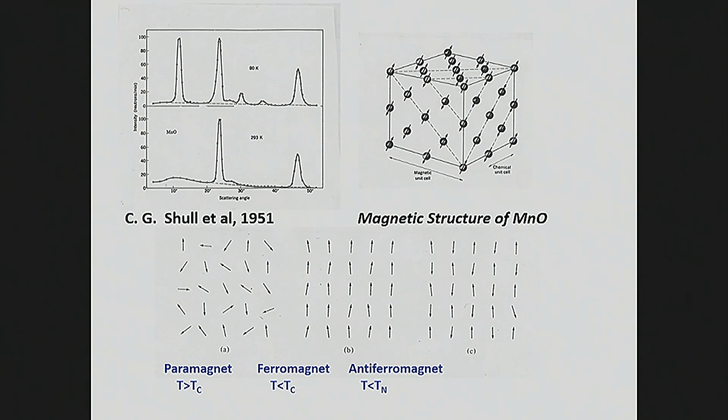So all magnetic materials, they form an ordered state, okay? And into antiquity, we knew about this ordered state. So this ordered state is what you get when you have these interactions between the magnetic moments, and we'll talk about those in a moment, which tend to form this parallel arrangement of the magnetic moments, okay, which is ferromagnetism, okay? And if you go to high enough temperatures, you go out of an energy-dominated regime to an entropy-dominated regime, and the magnetic moments become random. Okay, so you get a phase transition from this disordered magnet to this ordered ferromagnet, and that's what gives us compass needles and all that sort of stuff, fridge magnets, all those good things.